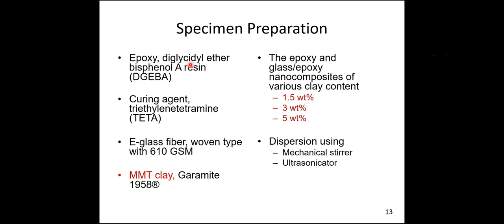Now, as I mentioned earlier, we cannot blindly mix the clay with epoxy. So we need to take some different clay content. Based on literature survey, we have chosen 1.5 weight percentage, 3 weight percentage, and 5 weight percentage nano clay. That means, for example, if I take 100 gram of resin, I can take 1.5 gram of nano clay and then I can mix. So this is called 1.5 weight percent epoxy clay nanocomposite. Similarly, I can have 3 weight percentage and 5 weight percentage nano clay epoxy nanocomposites.